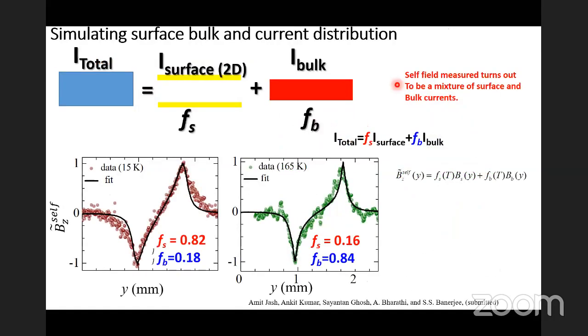And the way we analyze this self field distribution is that we consider the total current is made up of a fraction of the current which is flowing on the surface, which is called Fs, and the fraction of the current which is flowing in the bulk. So we consider 2D surface sheets of current, and we consider 3D bulk current, and we calculate the field which is generated by these surface and bulk currents for different fractions. The self field is fitted with this sort of a model where you have surface current and bulk current, and you can actually measure how much is the fraction of current on the surface, and how much is in the bulk.